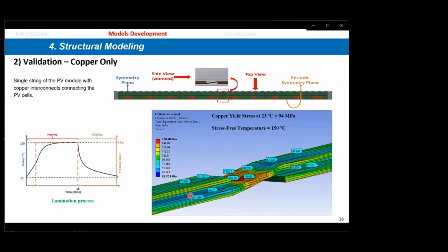Now, to include the initial conditions coming from the processing or the making of the PV panel, we looked at the lamination process. The lamination process consists globally of heating and then cooling. But when you cool, of course, the copper has suffered deformation, because you can see the residual stresses here, or the thermal stresses from the cooling after lamination, is about 158 megapascal, which is much higher than the yield point. The yield point is about 94 megapascal for the copper. So this means that during the lamination process, the copper interconnect has suffered plastic deformation. So we have to account for these initial or residual stresses in our calculations.